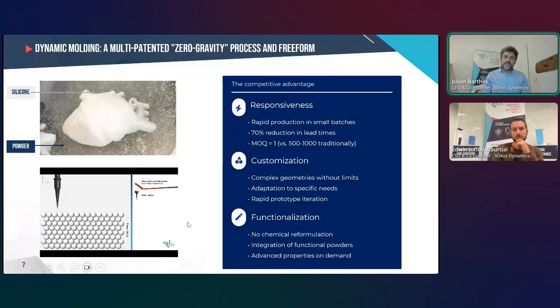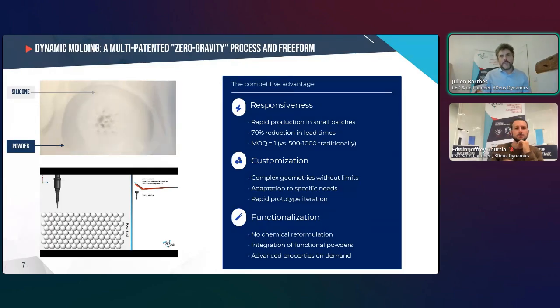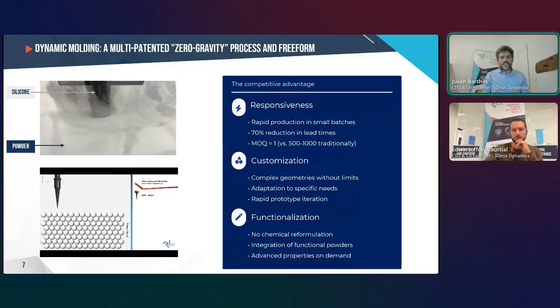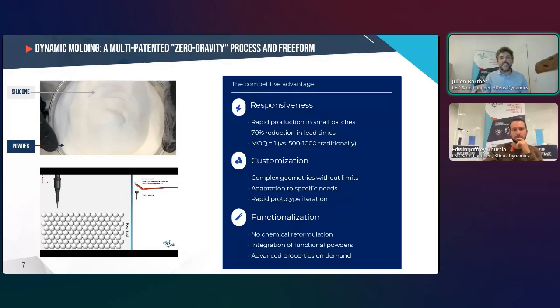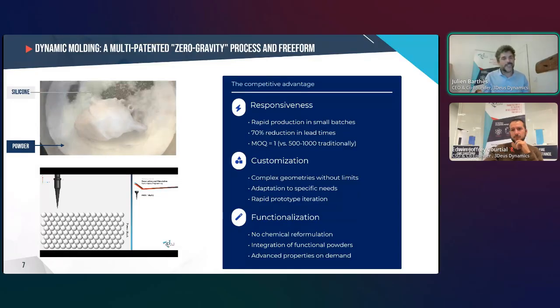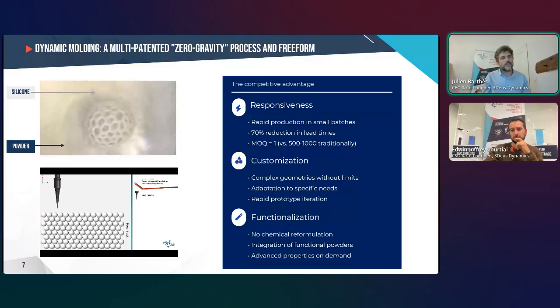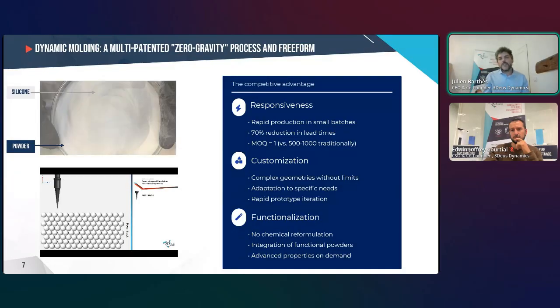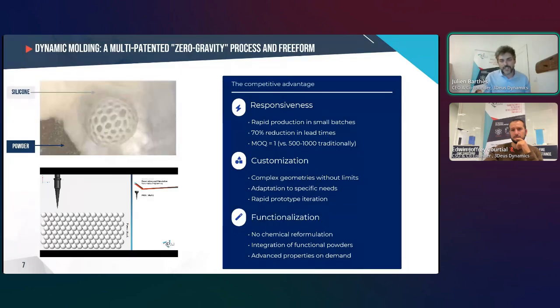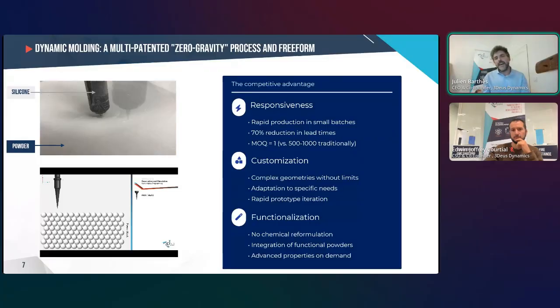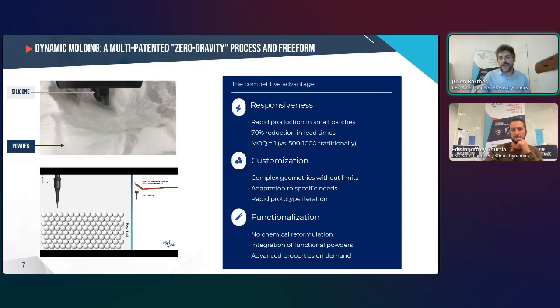So in terms of competitive advantages, rapid production in small batch, 70% reduction in lead time. And what is great for aeronautic and defense, the minimum quantity is 1, compared to molding where it is like 500, 1,000 or even 10,000 minimum quantity. And of course, you can customize the object the way you want. And what we are now the only ones to do is that you can really functionalize the material. So you can bring whatever property you want just by playing on the silicone on one part and the powder in which you print on the other part.